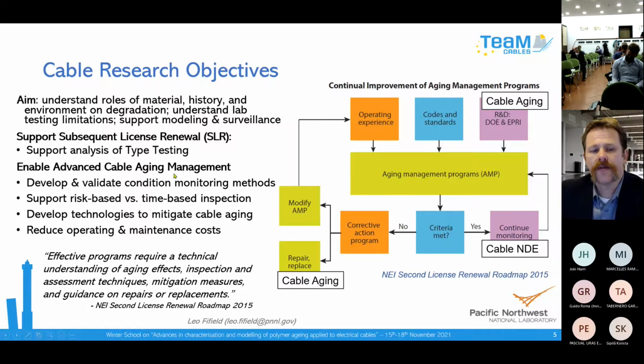So what I want to emphasize is in the original qualification for 40 years, safety-related cables were qualified for 40 years. And the way that they qualified the cables before the plants came online at the beginning was to do accelerated aging in the laboratory at elevated temperatures and high dose rates, to impart effective 40 years of aging on the cables, and then do design basis event testing, loss of coolant accident testing, to see if the cables will survive that. And if they had the 40 years of equivalent aging and then they survived the testing, then they could be